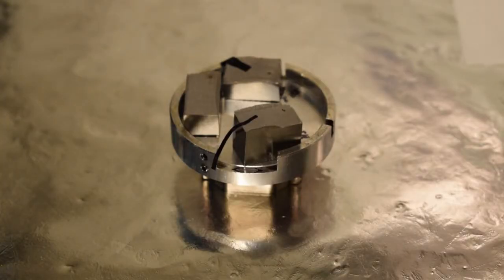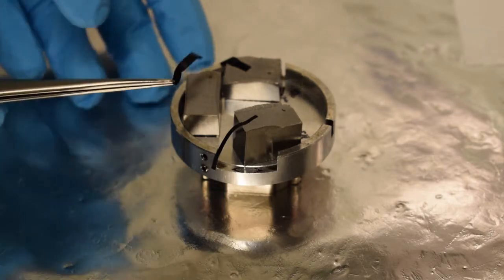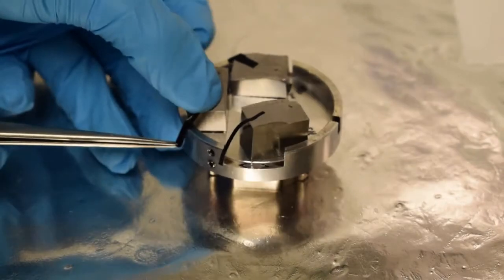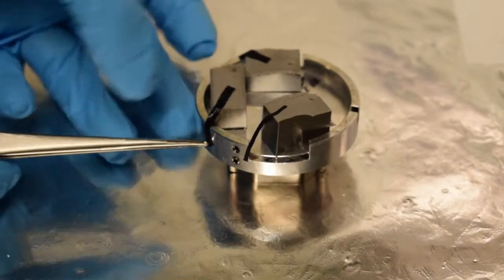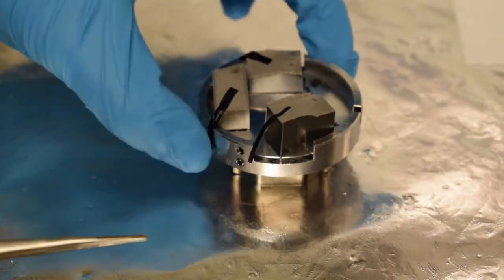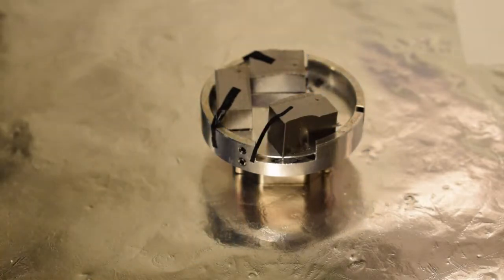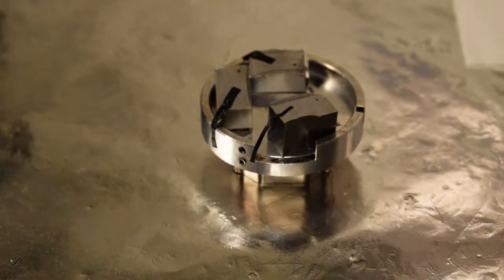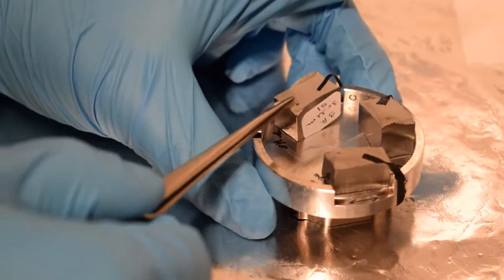In over 60 fatigue tests, the ESHM system always detected the presence of a fatigue crack before final fracture of the component. But fatigue testing reveals more than the proof of concept of the ESHM system. It allows to analyze the effect of the capillary on the structural integrity of the part.